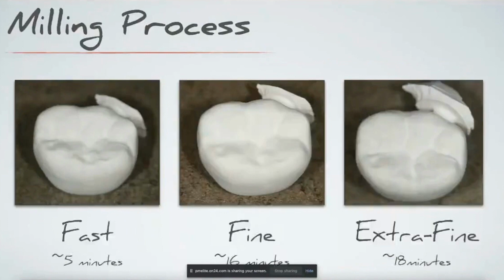And I'd have another 8 or 10 minutes just for the milling process, much less the other polishing that would have to occur. So when we compare these, again, I'm living on the left side of the screen in my practice, okay? It's myself, it's 2 associates. We're using multiple milling machines, multiple scanners. But even with that, I want to generate the restoration and have it ready to go. So the one on the left is still going to require post-mill processing. So is the one on the right. But I can save myself 13 minutes plus of time by milling it in the fast mode, having the assistants polish this, define the anatomy, and get it sintering in the furnace, and then be out and ready to deliver for the patient.